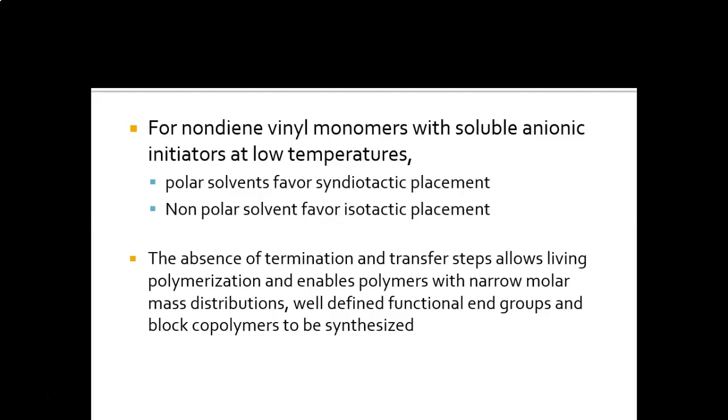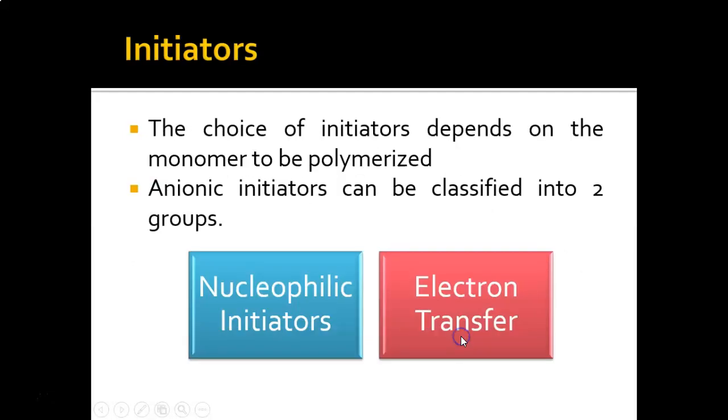A polar solvent will favor the syndiotactic placement, which is the arrangement of the polymer in an alternate structure, alternate placement, and a non-polar solvent favors the isotactic placement, which is the same side of the side group. The absence of the termination and transfer step allows living polymerization and enables polymers with narrow molar mass distribution, well-defined functional end groups, and block copolymers to be synthesized.